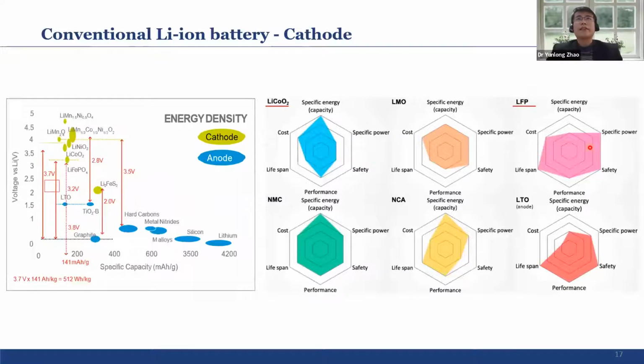So this is just the anode side, and here is the cathode. As I have already shown, this figure shows different cathodes. Commercially, we use lithium cobalt oxide and lithium iron phosphate, and there are some other types of cathode. By the way, lithium titanium oxide is usually considered an anode, especially compared with the NMC. That is the lithium, manganese, cobalt, nickel oxide.